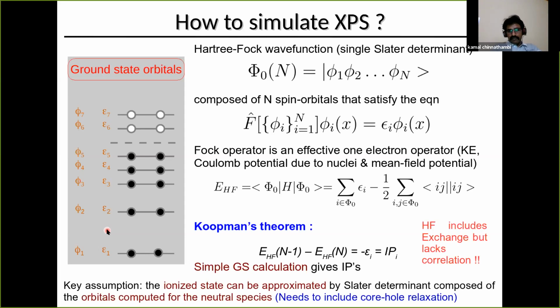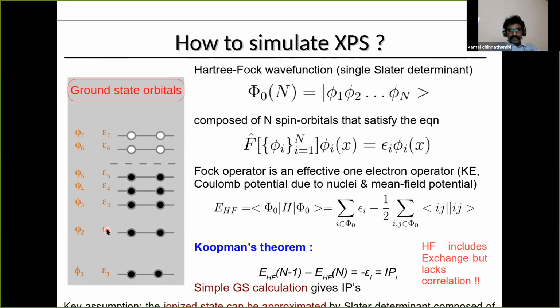Another thing is that, by using Slater determinants, we incorporate the exchange, or the Pauli exclusion principle, in a correct manner, but it misses the correlations. So how do we go about it? Also, for periodic systems, especially the slab model I am talking about, which has such a big size, typically around 450 atoms in a supercell, you need to go for much simpler computational methods. So we choose DFT because it has very good scaling.